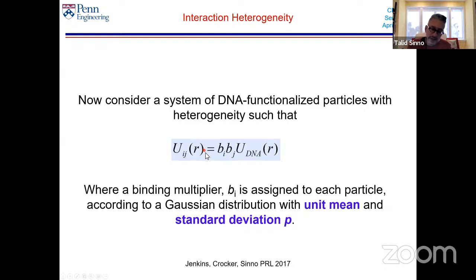Each particle has this factor B that says I either have more or less than the average number of strands on me, and therefore a pairwise interaction becomes Bi times Bj times the mean interaction strength. So this is something we call interaction heterogeneity, and we're very interested in this effect because it seems to have a profound impact on self-assembly.